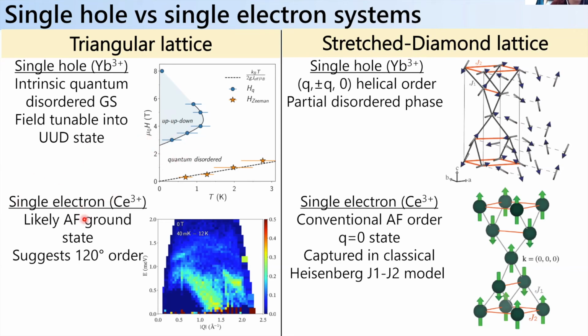Whereas if I were to swap out the ytterbium with cerium, then I have a system that seems to acquire the likely 120-degree ordered ground state of that material. And on the stretch diamond lattice, again, the single hole system acquires this sort of highly frustrated helical order. But it also seems to have this intermediate partial disordered phase that we're still working to understand. But in the cerium version of that, it's sort of just a vanilla antiferromagnetic ordering, with a small degree of magnetic frustration. And it's sort of not the more interesting of the two.